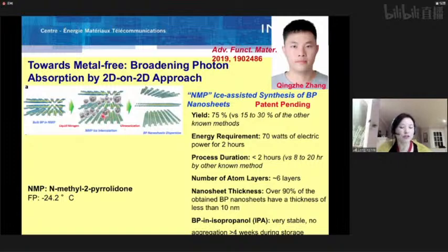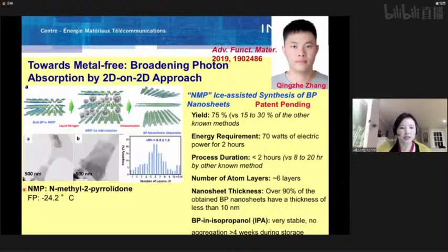For 2D BP nanosheets, the synthesis is kind of difficult. I mean, large scale, high yield synthesis is kind of difficult. So this brilliant student developed a new method. We call it NMP-assisted synthesis of BP nanosheets, and the work is currently patent pending. In this synthesis, what he did is introduce tiny ice nanocrystals into the BP structure to decrease the interaction between BP sheets to help exfoliation of BP nanosheets.